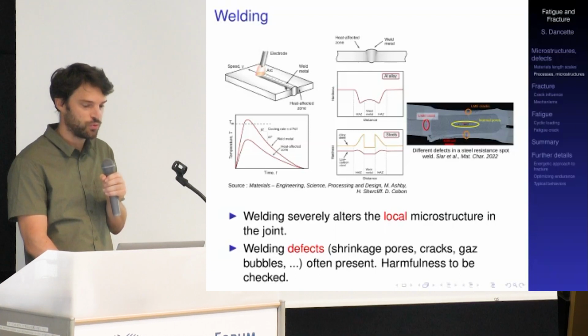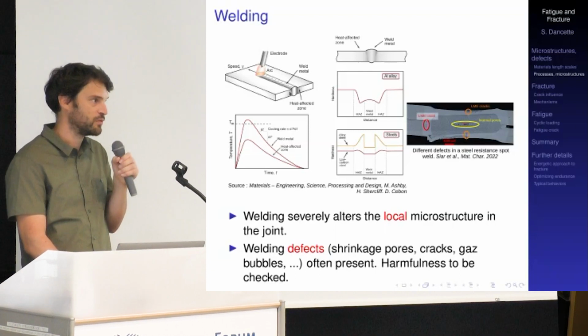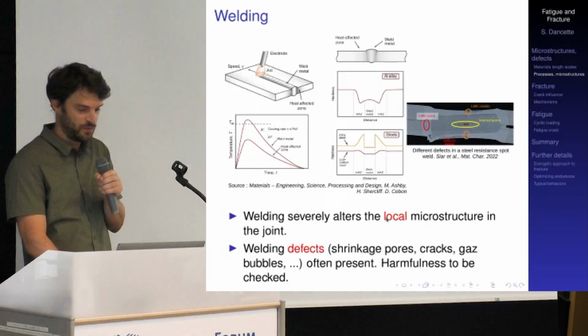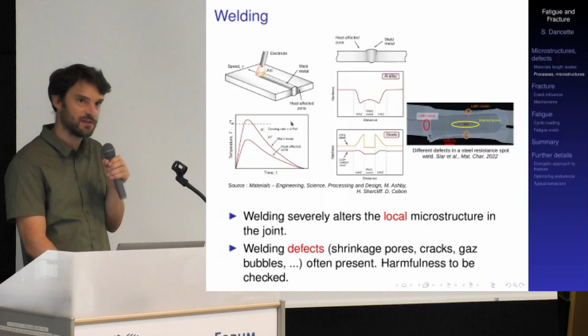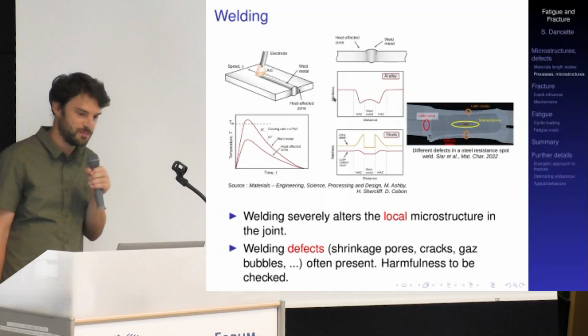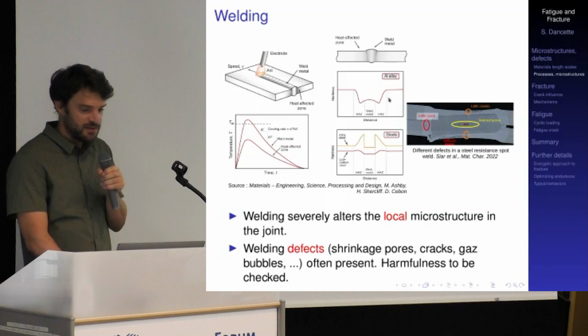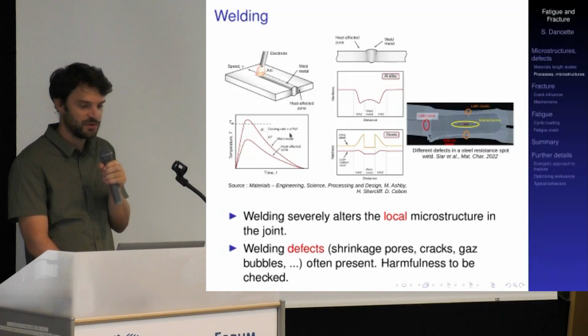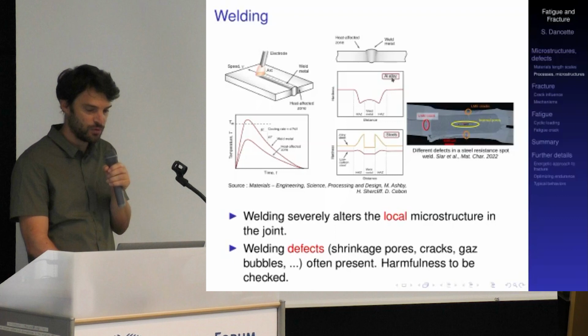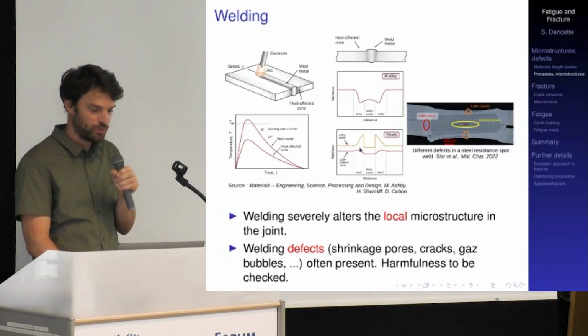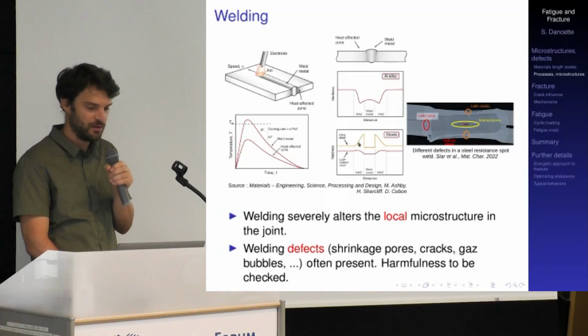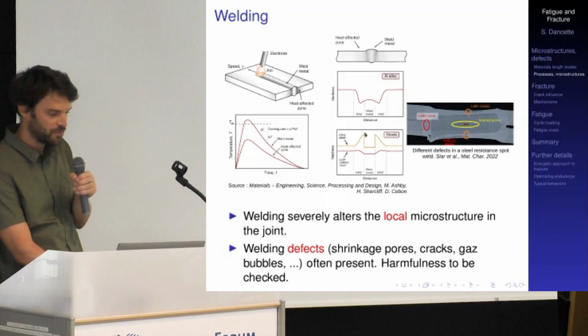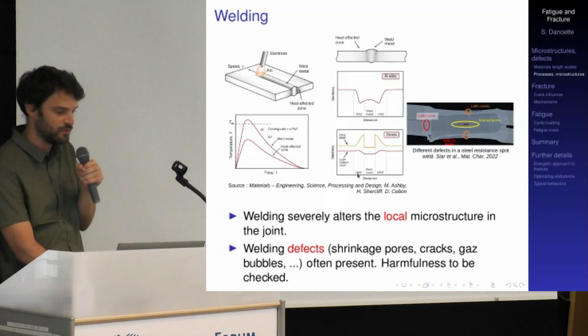And again, during the welding process, there will be some strong evolution of the microstructure, and especially evolution of the local microstructure, so the local microstructure of the weld compared to the microstructure of the base metals of these parts. And this is due to the thermal cycles that are experienced locally in the weld, and depending on the type of metallic alloy, aluminum alloy, for example, or steel alloy, you will have different types of evolution of the local mechanical properties. So this is the example of an alloy steel, where you will experience some strong hardening in the so-called heat affected zone here in the vicinity of the weld.